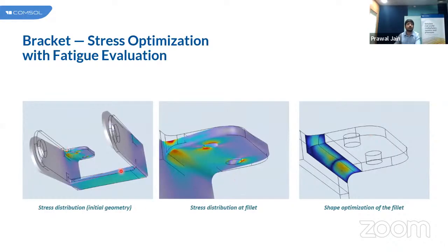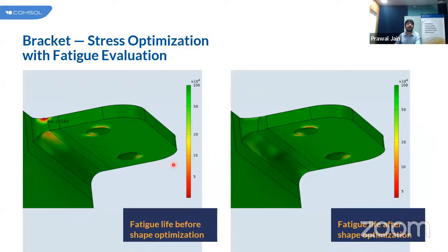So here we can see the overall stress distribution over the bracket. There was quite a high stress concentration near the fillet, but with shape optimization, we can see that the fillet radius in this region as well as in these regions has been improved or changed by the automatic solver. Comparing the results, previously this fillet end was failing. But after shape optimization, this shape is a little bit changed, which led to an increase in the fillet radius, and which basically increases the life of this bracket from the fillet end where it was failing at the earliest.